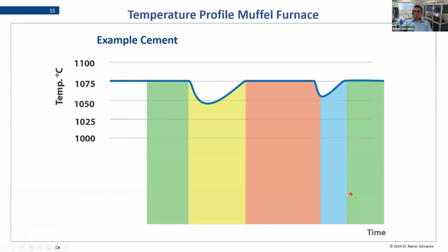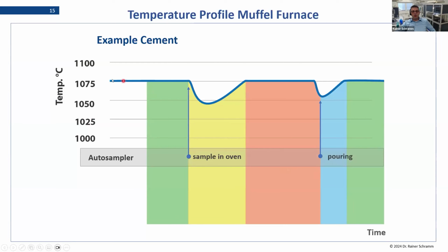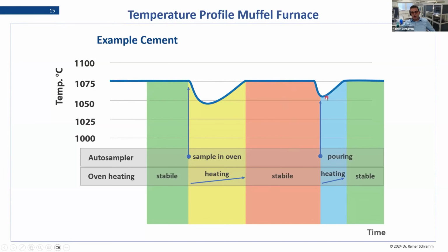Okay, but let's now talk about temperature. If we look in a muffle furnace, we have the situation that your furnace is performing at a certain temperature, so it's stable. But in the moment you open the door because you want to introduce a sample, the temperature has to go down, of course. So you destabilize the whole system. You close the door again, and then, of course, the system will reheat and will form again a stable temperature. But when you want to get it out, same story again, and the temperature will drop.